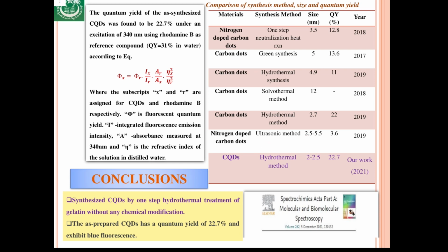We were able to synthesize these carbon quantum dots using a simple hydrothermal method requiring no chemical processing or purification, and the size and the quantum yield of our carbon quantum dots were found to be comparable to these parameters reported earlier.